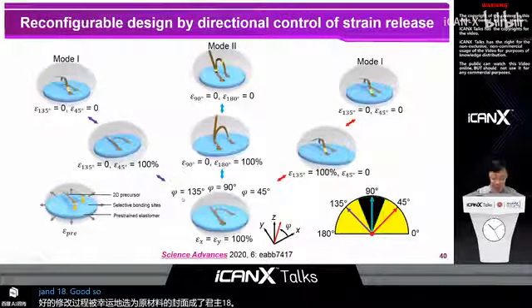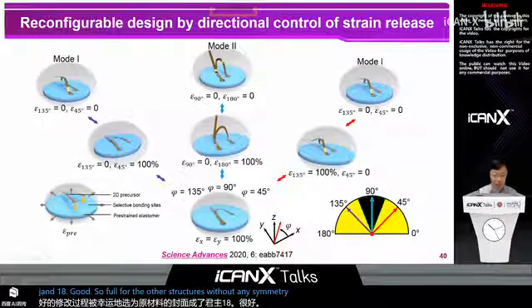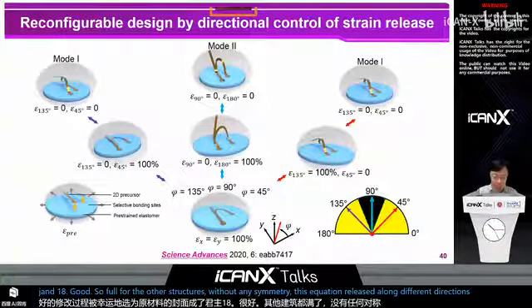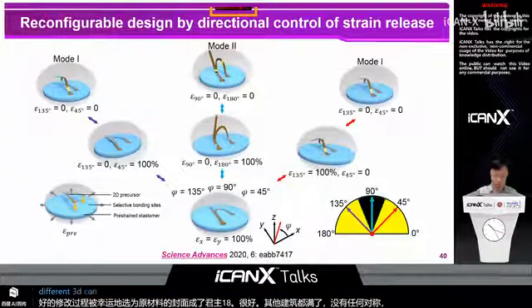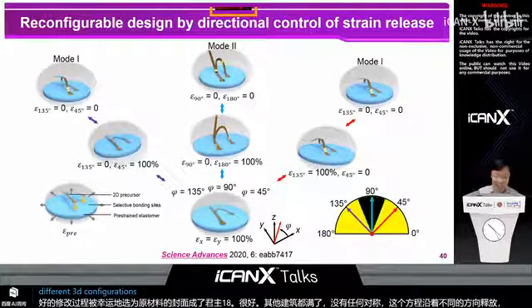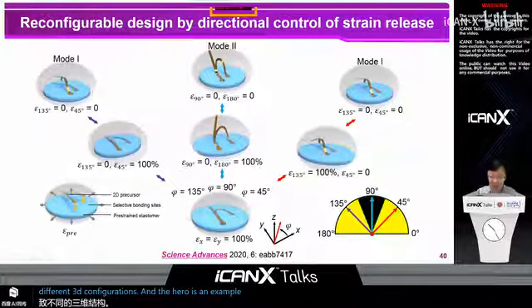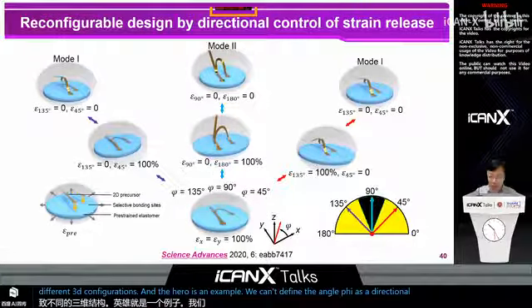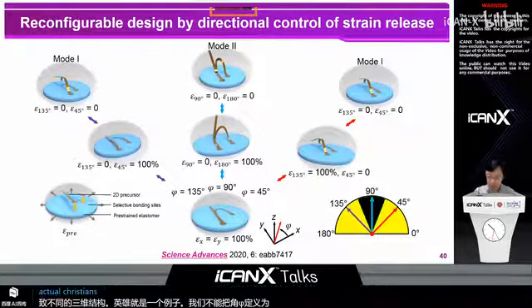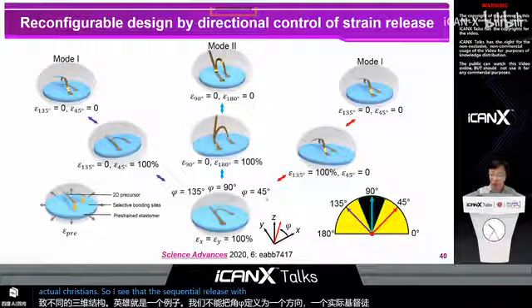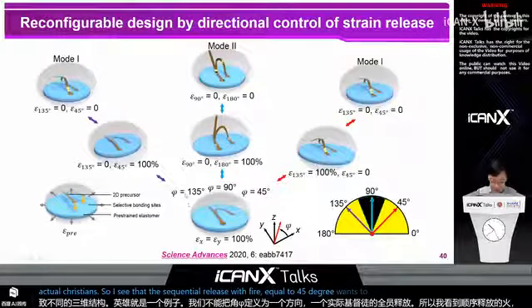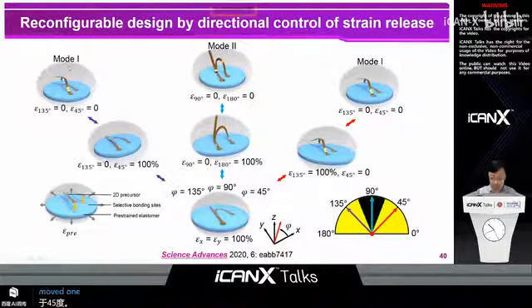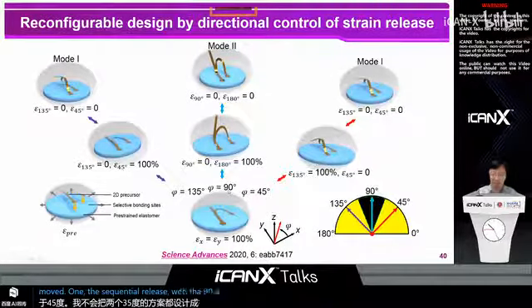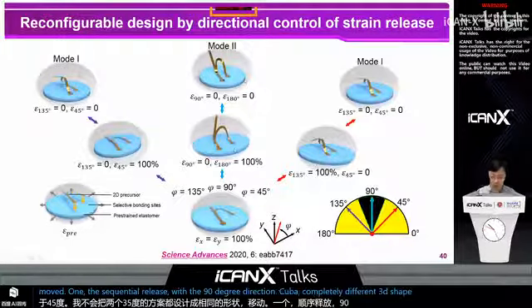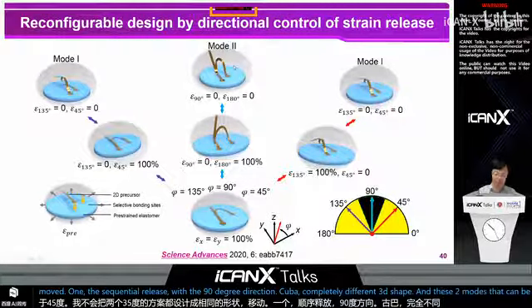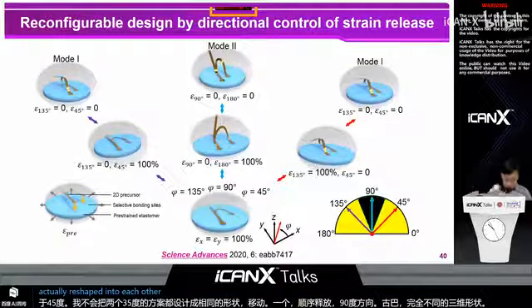So for the other structures without any symmetry, the sequential release along different directions may induce different 3D configurations, okay? And here is an example. We can define the angle phi as the direction of the first step release of the biaxial pre-strain. So you can see that the sequential release with phi equal to 45 degree or 135 degree both give the same shape, mode 1. But the sequential release with the 90 degree direction give a completely different 3D shape, mode 2. And these 2 modes can be actually reshaped into each other reversibly, okay?